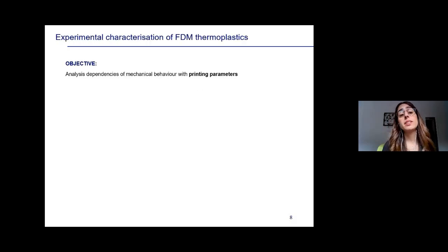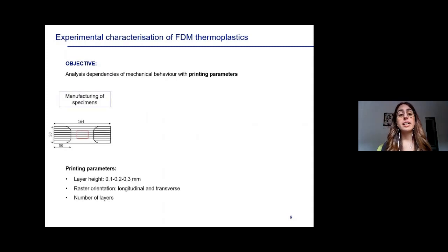As I said, the objective of this one was to analyze the influence of different printing parameters on the mechanical properties. And for that, the first thing that we did was manufacture different specimens using different combinations of printing parameters. We studied the influence of 3 of them, which were the layer height. We used 3 different layer heights, 2 raster orientations, and different combinations of the number of layers.